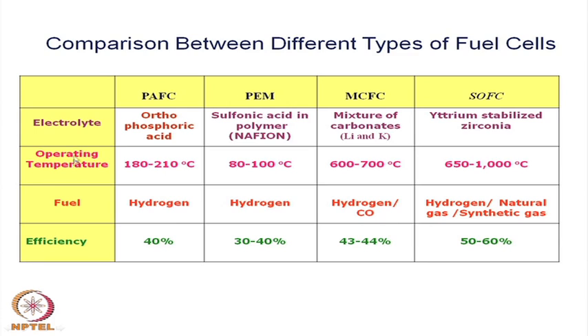The operating temperature of PAFC, or the phosphoric acid fuel cell, is about 180 to 200 degrees, whereas PEM fuel cell, or polymer electrolyte fuel cell, has an operating temperature of around 80 to 100 degrees centigrade, because beyond that the polymer is not stable. So, one has to limit to this kind of an operating temperature.